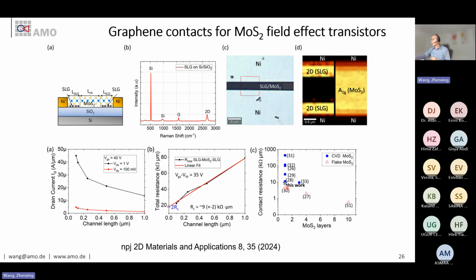But of course, you see this star is our result from this work, and the triangle. We have still work that shows lower contact resistance here, but they're all from flake MoS2, so not from CVD. Usually CVD MoS2 has worse quality, so this also limits the contact resistance. So basically what we can achieve is really the best among all the scalable materials, meaning CVD materials.